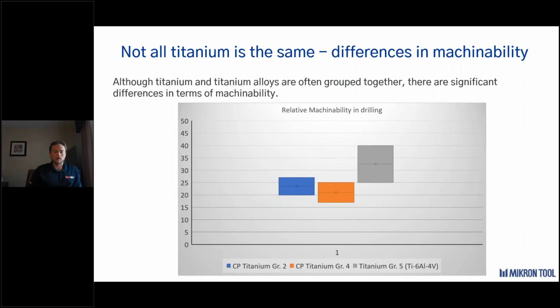Commercially pure titaniums, much more gummy, much more sticky, have a real tendency to build up on to the drill itself, weld itself, and present a gummy condition. Alloy titanium is much stronger. You have to have a little bit different of a cutting geometry to approach that stronger tensile strength material and create a chip effectively. But this is something that our R&D lab spent a lot of time to develop one drill for both these materials.